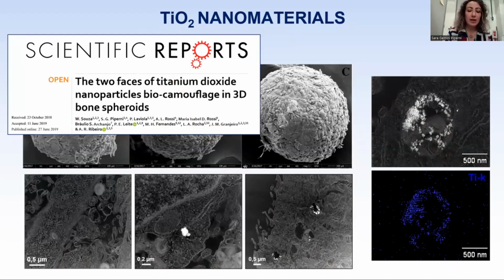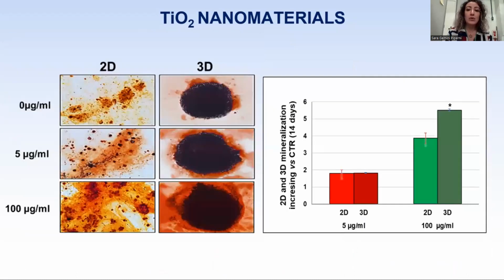And then what we are doing now is looking at what happens with the mineralization in monolayer and in 3D model. And we found an increase of mineralization after exposition to higher titanium nanoparticle doses in the 3D model compared with the monolayer. But no significant difference was observed between the 2 models regarding the mineralization after low titanium dose exposure.